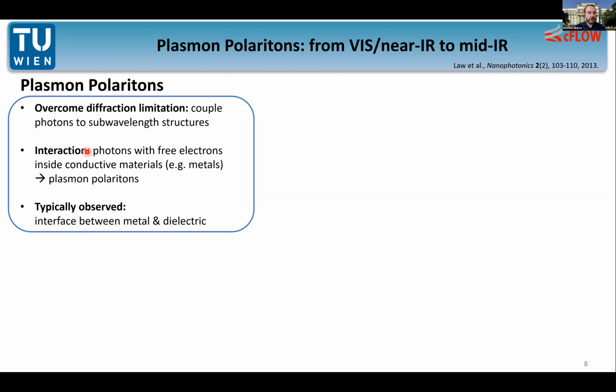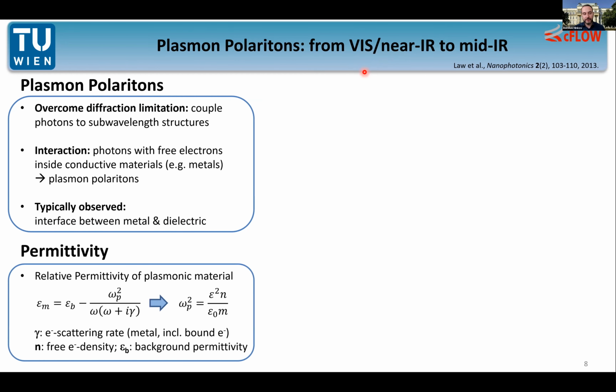So by an interaction of photons, so of light, with free electrons inside the conductive material, which is an elegant way to say inside a metal, we can have excitation of plasmon polaritons. So if you look, for example, at an interface between a metal and a dielectric, at this interface, we can excite plasmon polaritons. Historically, they have been first realized and used in the visible spectral range and in the near-infrared spectral range, but now we also want to use them in the infrared spectral range. We're going to see in a second what has to be modified for them.